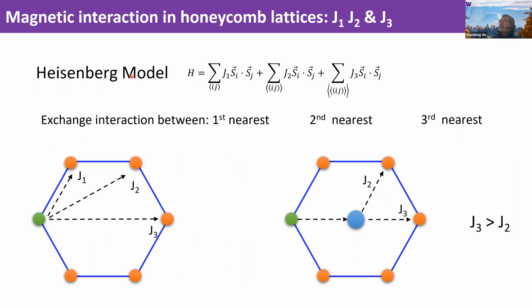This class of material, MPX3, belongs to the honeycomb lattice, and we can look at the Heisenberg model, which is used to describe the magnetic interactions in these honeycomb lattices. Here I show three terms: J1, J2, and J3. J1 represents the first, the nearest neighbor exchange interactions, as I show here. J2 is the second nearest, and J3 is the third nearest exchange interactions.